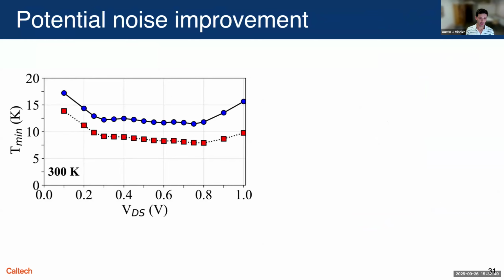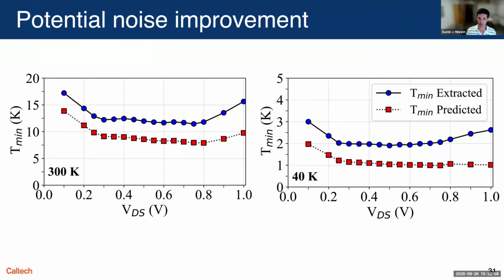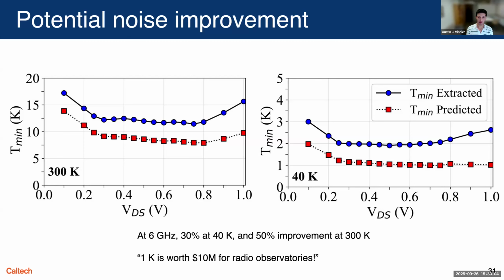Now, how good could we do if we were able to eliminate that additional hot electron noise source? So this is a plot of the minimum noise temperature versus VDS. The blue symbols are from the model. The red symbols are if we remove this noise source. So you can see in room temperature and 40 Kelvin, something like a 30 to 50% improvement depending on the particular conditions. And for radio astronomy, again, 1 Kelvin is $10 million. So the radio astronomers here are quite excited about the potential here. Okay, and what we're doing now is making HEMTs and trying to realize that.